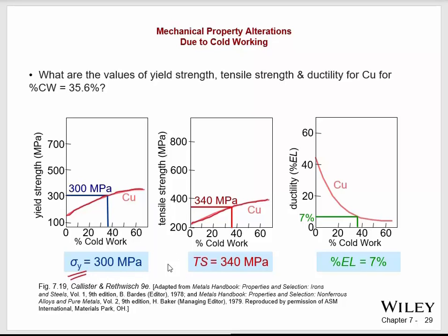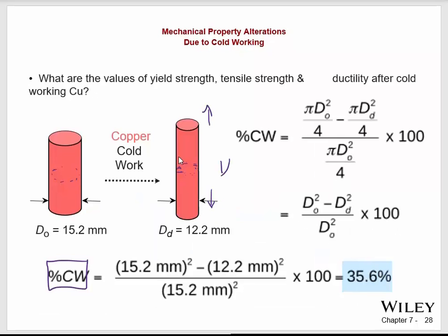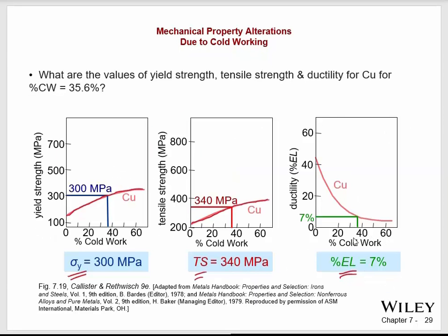So we can analyze it in the dimension of yield strength and tensile strength and see how those increase. And we can also analyze it in terms of percent elongation. So remember, do not confuse percent elongation with how much this has lengthened. It's actually more related to how much it has left to go before it snaps, right? So the smaller the percent elongation you have, the less ductility you have. So this is a measure of ductility, and these are a measure of how hard you can tug on something without it changing or breaking, right?